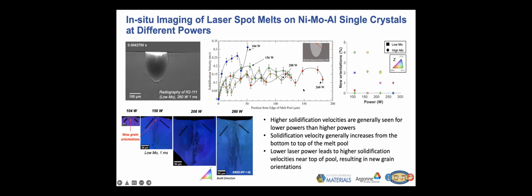We can see some general trends that fall out. At the high power conditions, overall, we tend to have lower solidification velocities. At the lower power conditions, we tend to overall have higher solidification velocities, and solidification velocity tends to increase from the bottom to the top of the melt pool.